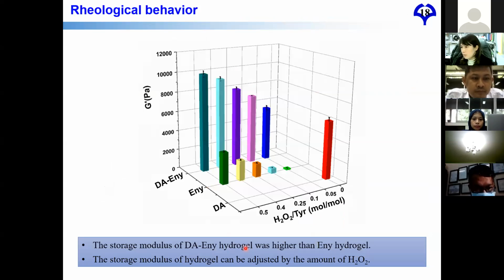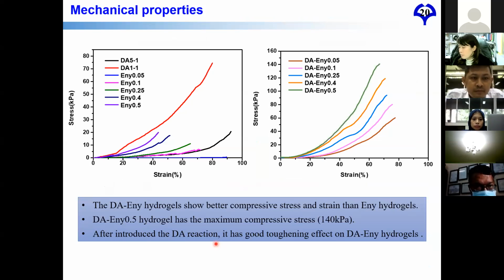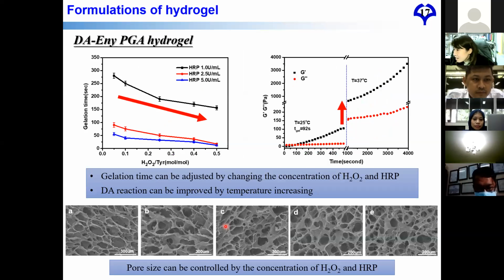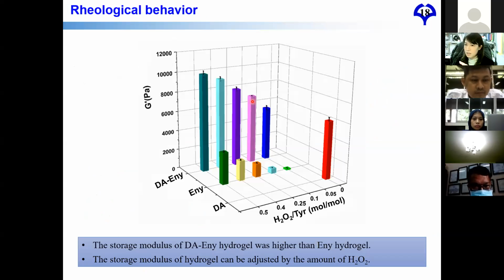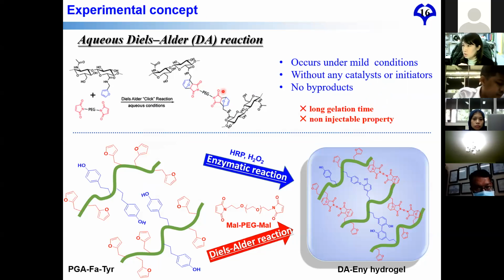So in this study, we want to also increase the gel strength using the Diels-Alder reaction. This Diels-Alder reaction has also been used before. However, the Diels-Alder reaction has a problem because the gelation time is very long, and it cannot be injectable.